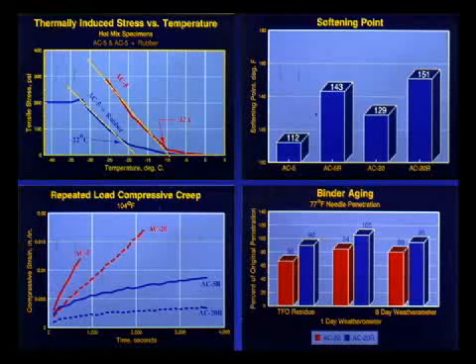Over here we have softening point. Again, these are big changes when you look at how the material behaves in the field. The softening point tells you that in hot climates it's going to stay stiffer rather than becoming fluid. Down here we have the repeated load creep test, and basically what this is showing you is the ability to resist rutting.